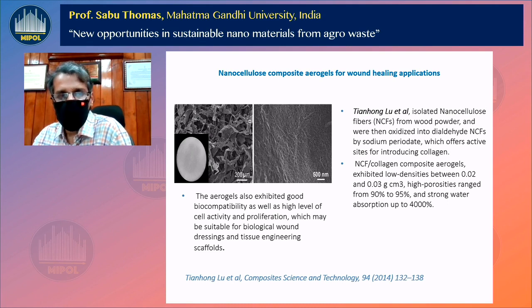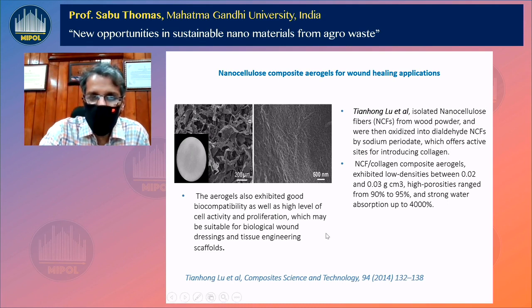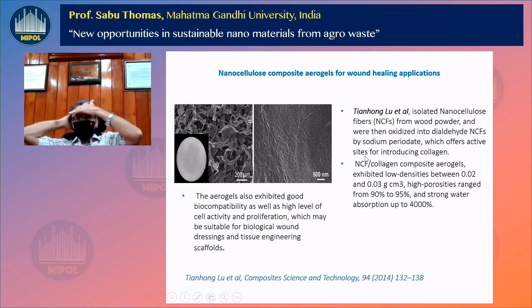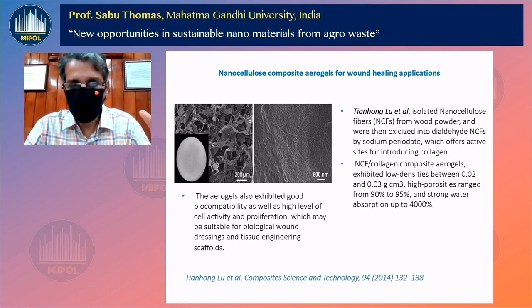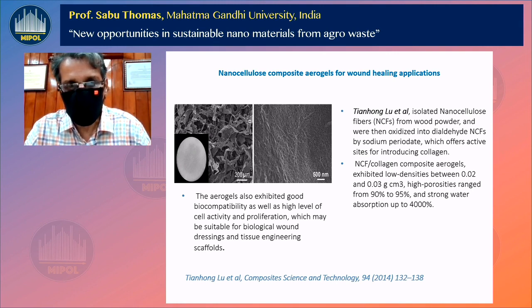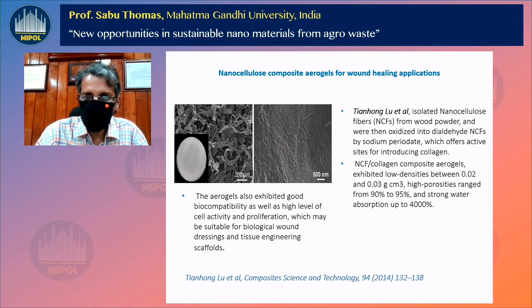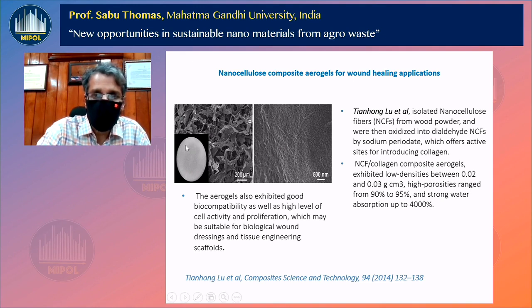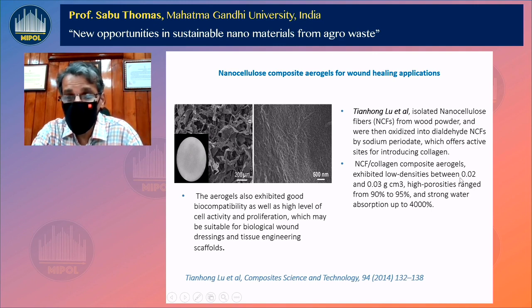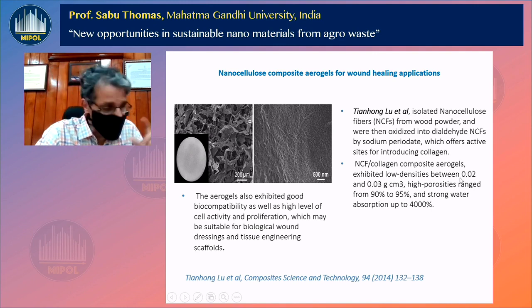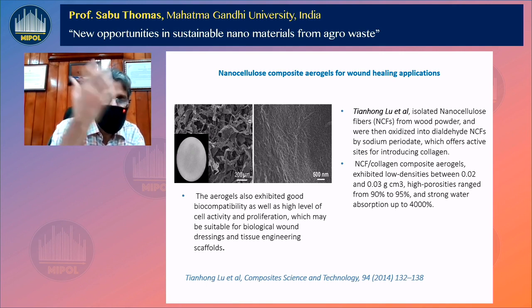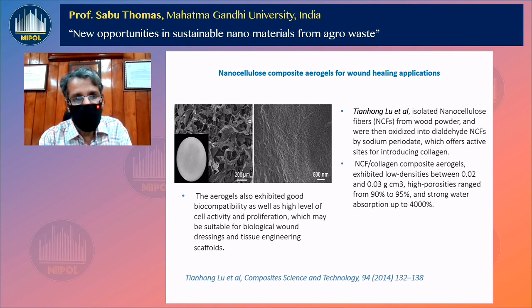Professor Liu did something very interesting. Professor Liu combined nanocellulose and collagen together. When you combine both nanocellulose and collagen, you get a wonderful platform which is extremely biocompatible. He made aerogel. Look at the aerogel made by Professor Liu. And the density of this aerogel is 0.02 to 0.03 gram per cubic centimeter. Very, very light. Porosity is between 90 to 95%. And look at the water absorption capacity, 4,000%. And Professor Liu said this is an excellent material for wound dressing.